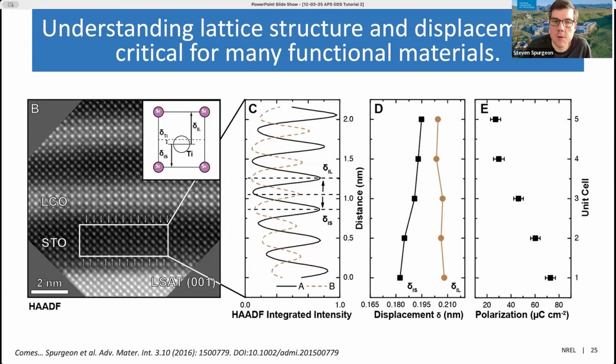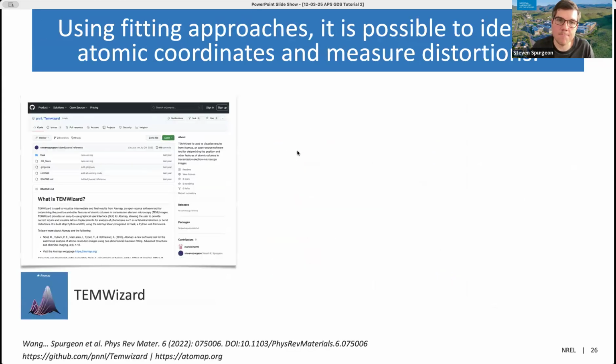Traditionally, what we would do is conduct imaging. We would take great pains to ensure that our drift and other distortions are minimized. Then we literally perform a linear profile of that intensity across the superlattice. The goal here is to quantify the positions of the different sublattices, measure displacements, and then from that calculate polarization. Now, this has worked successfully, but it's a very crude way to do any kind of measurement. The important thing is that this is a hyperlocal measurement. It doesn't really encompass a lot of the variability that we would see across a broader interface, which we know is absolutely important to understanding device performance.